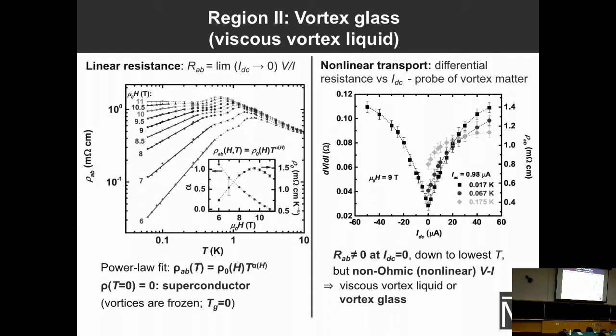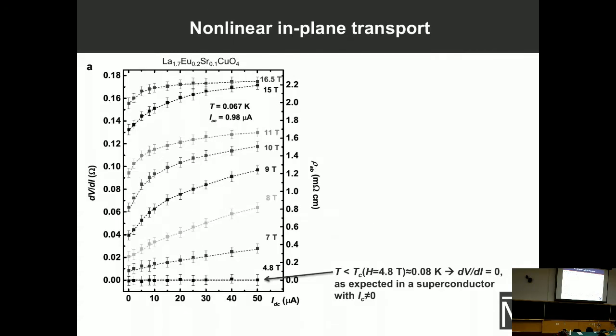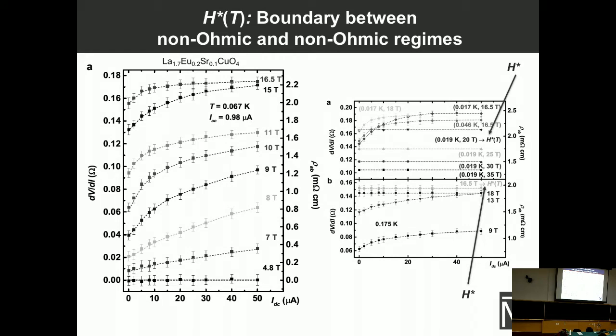We have performed these measurements over the entire range of fields and temperatures, and here is just one example. For example, at the lowest fields, the resistivity is 0, because here we are below TC and below the critical current. But when we get into this vortex glass regime, we are measuring finite linear resistivity, but the VI is nonlinear, and if you keep increasing the field further, I know this is hard to follow, but basically at some field, these curves will become flat.